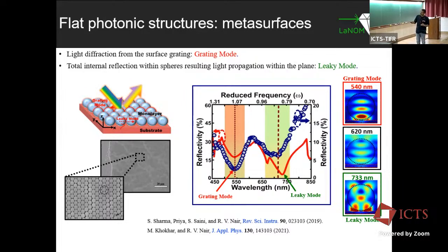So you have a substrate, and this is one of 700 nanometer microsphere on the substrates. When you shine light, you see two dips: one is a grating mode, because there is a subwavelength grating, and the other mode, close to 733 nanometer, can localize some field between these spheres and the substrates. That means this is a low index metasurface, which can affect the NV center emission properties.